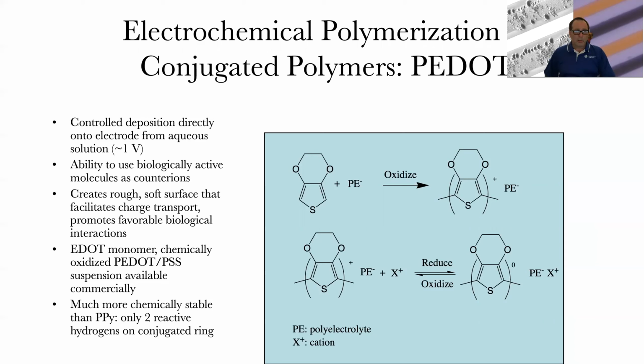We like to use electrochemistry because electrochemistry allows us to do the oxidation polymerization reaction right on the electrode surface so we can direct where it goes. We can tailor the counterion quite easily, and we can then create also very precisely tailored films that have different morphologies by using, say, dissolvable substrates or different constructs that we grow the polymer around. And in fact, we've even done this polymerization in living tissue. So we've grown the polymer in the brain, we've grown it in the hippocampus, we've grown it in peripheral nerve, and that's one of the other interesting angles that can be explored here.